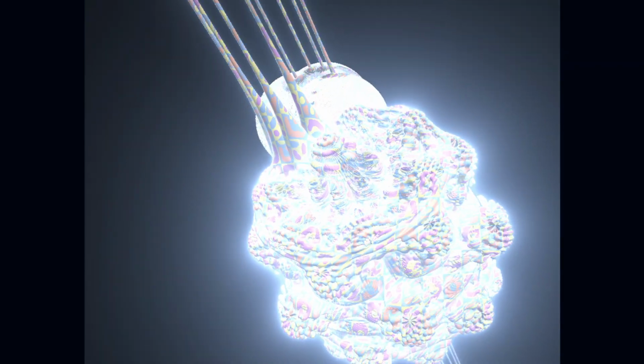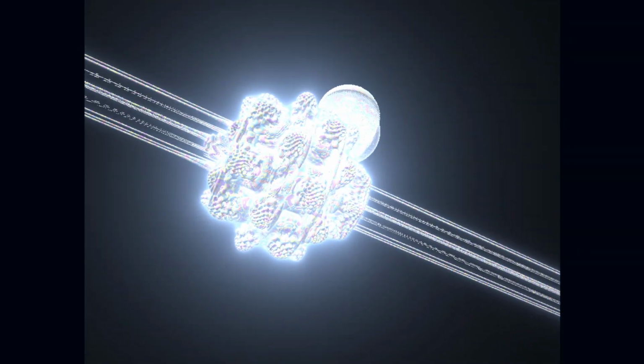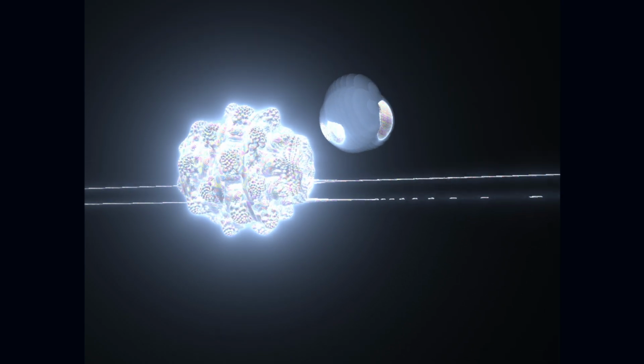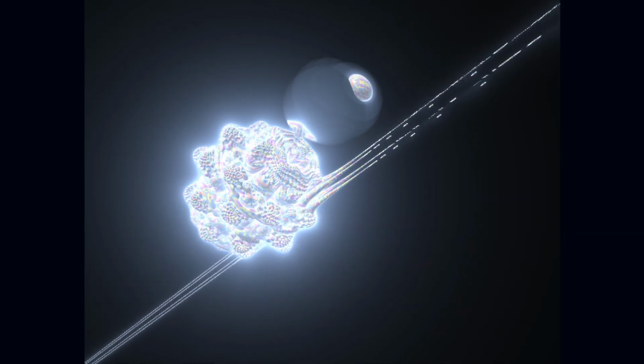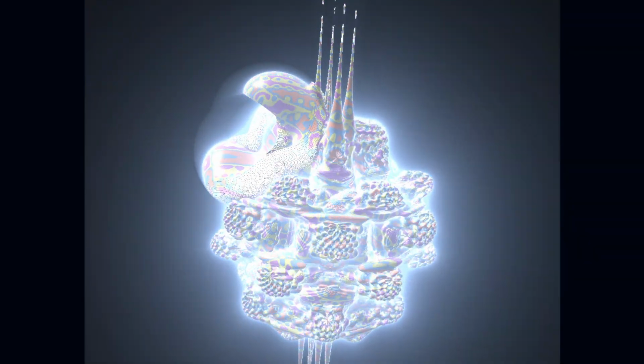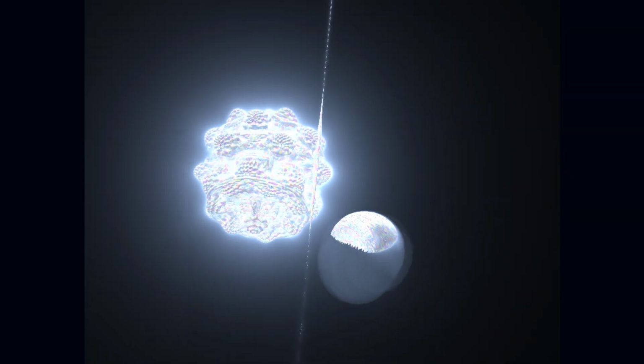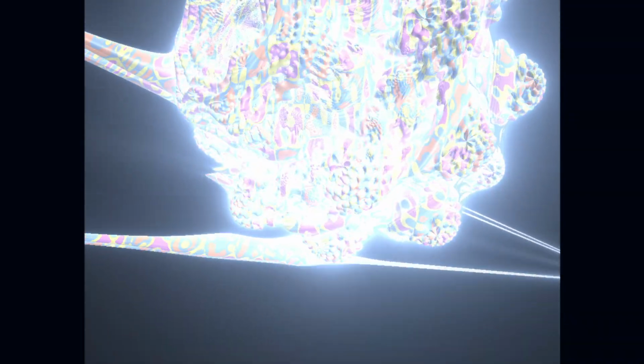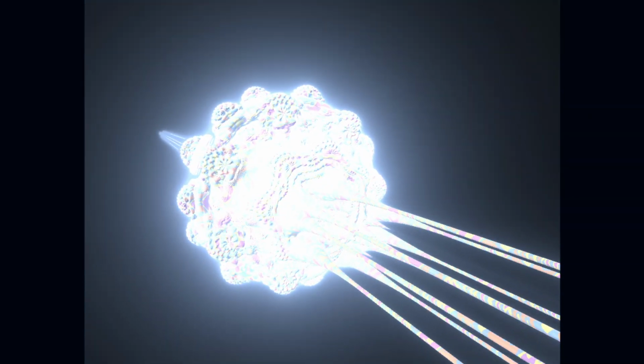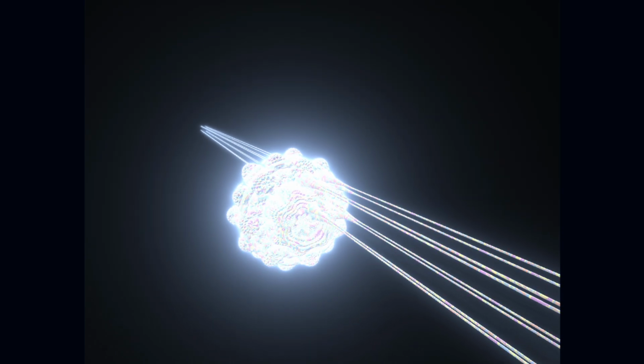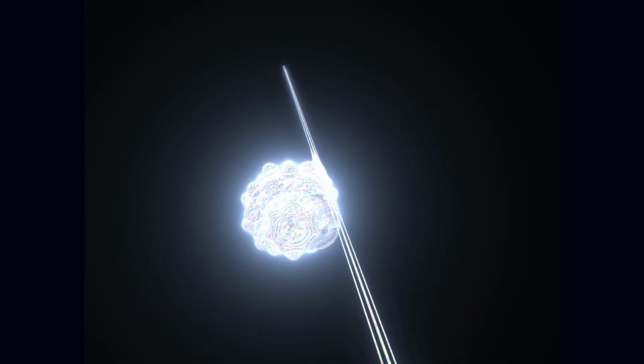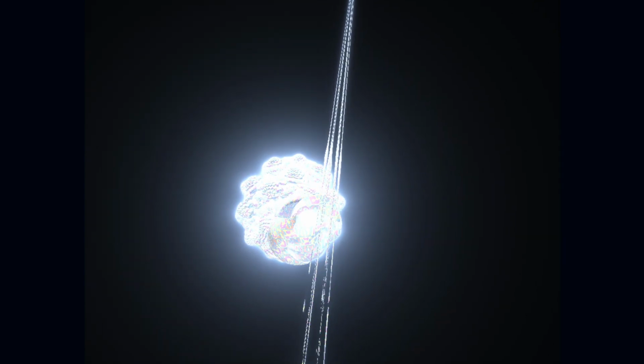It really is. And we see this clearly in materials. For example, let's go back to CsPbBr3. Yeah. Ab initio calculations, the bare theory, predict a hole effective mass of about 0.17 times the free electron mass. Okay, 0.17 bare. But high-resolution ARPES experiments directly measure a significantly heavier polaron mass of 0.26 plus or minus 0.02 times the free electron mass. So 0.26 measured, that's that 50% enhancement again. Exactly. And this experimental finding aligns beautifully with the theoretical predictions from the Feynman polaron model using the known alpha value. That model calculates 0.24. Wow. 0.26 measured, 0.24 predicted. That's a remarkable agreement, almost eerily accurate. It shows the power of both the theory and the experiment.